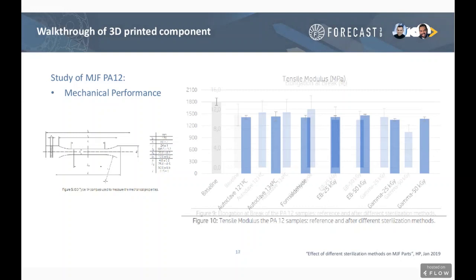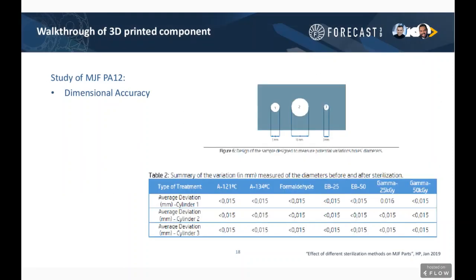The next one is the dimensional accuracy. So this was a test coupon designed with 3 different hole sizes, a standard coupon, and run through the same tests. So we have the autoclaves, we have the formaldehyde, we have the E-beams, and then we have the gamma radiation. And essentially, for the measurement being in millimeters, this is quite negligible. So we didn't see a whole lot of dimensional change from the PA12 in this process.